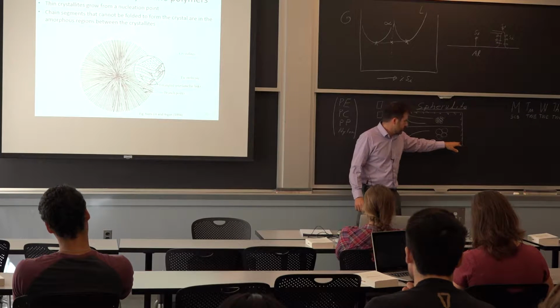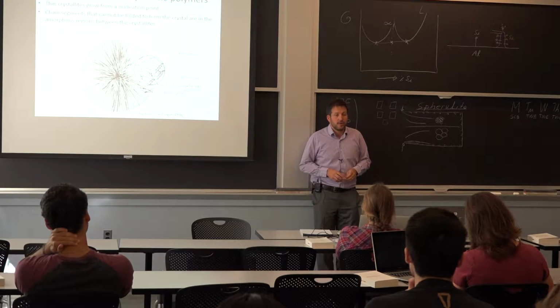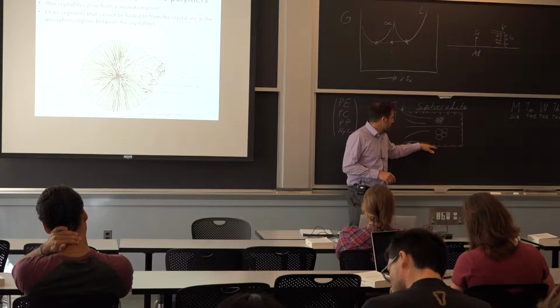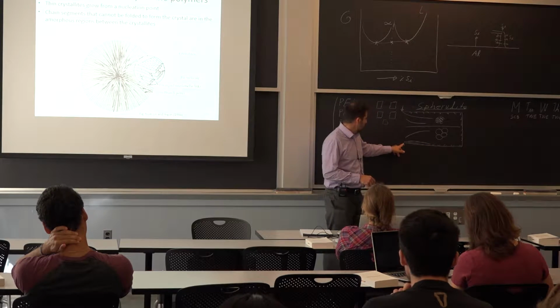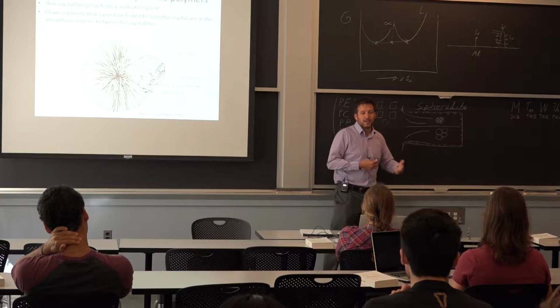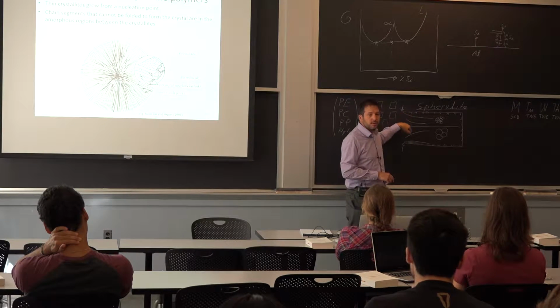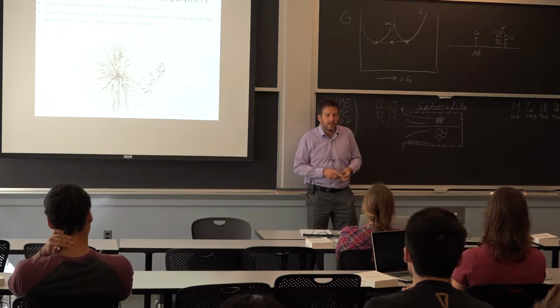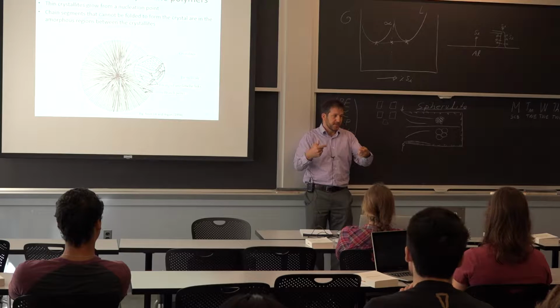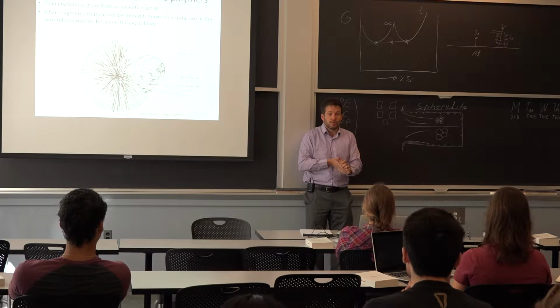The problem is it never gets as good in certain corners. It's going to vary, so you cannot necessarily rely on it that much. But if you are in the middle of the part and you have bending stresses here, the first thing you don't want is an injection molded part where you have high stresses. So you need to be in an area where you know that you will be gaining an advantage. And the worst is to be at the mold line where you have two injection ports that meet. It's very common in a complex part to have multiple injection points. So where everything meets, the polymer from one side doesn't really entangle itself as well with the polymer on the other side, and you get a much lower long-term strain.